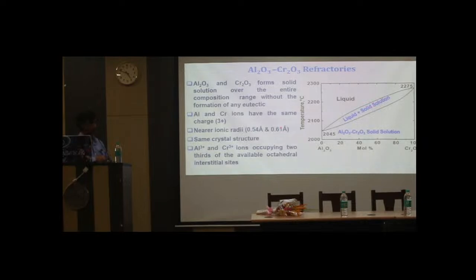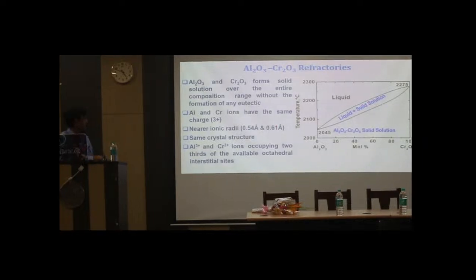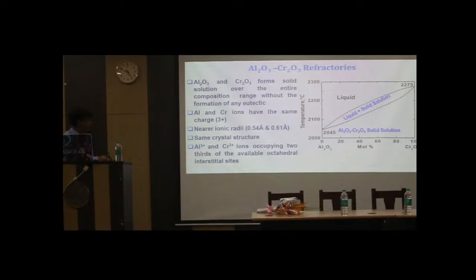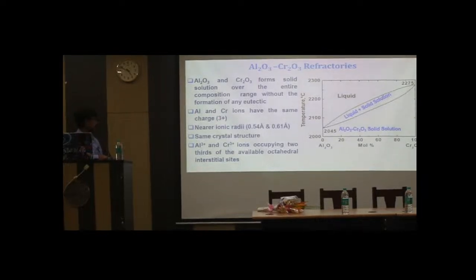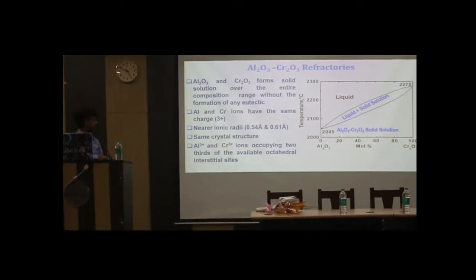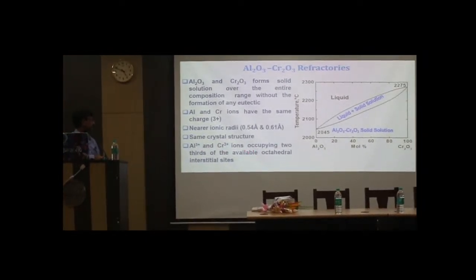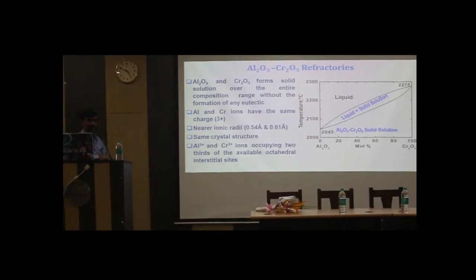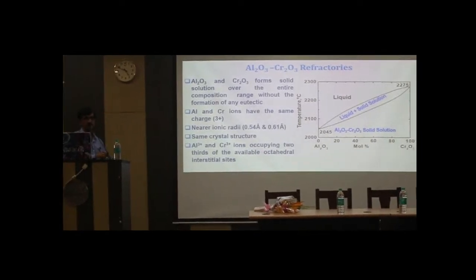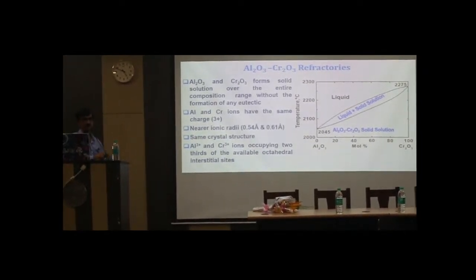Because alumina and Cr2O3 have a similar crystal structure, and the aluminum and chromium ions have the same charge, 3+, and nearer ionic radius. Aluminum and Cr3+ ions occupy 2/3 of the available octahedral sites. Due to the structural similarity, size similarity, and same charge, it forms a complete solid solution. It is ideal for solid solution formation.